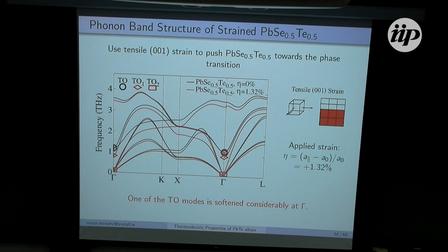Again, similarly to lead telluride, it's enough to push it towards the verge of the phase transition, but keep it in the tetragonal phase. And again, with that caveat that 1.32% of strain is rather a lot, this should probably be thought of more as a thought experiment of what happens when we push it towards the verge of the phase transition. And that TO mode again, soft.